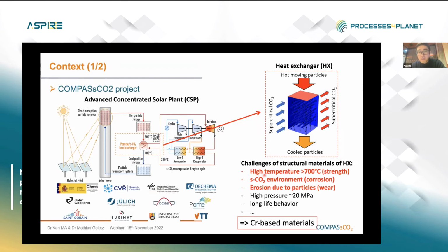For example, it needs to have high strength at high temperature, and it needs to be resistant to corrosion and oxidation, and also resistant to erosion by particles, and also it will operate at high pressure for a long time. And as you have seen, a lot of advanced materials were mentioned in previous presentations, including nickel superalloy, austenitic steels, ferritic steels, and some ODS steels. And in the Compass CO2 project, we have suggested also another alternative to this conventional material, which is chromium-based alloy.